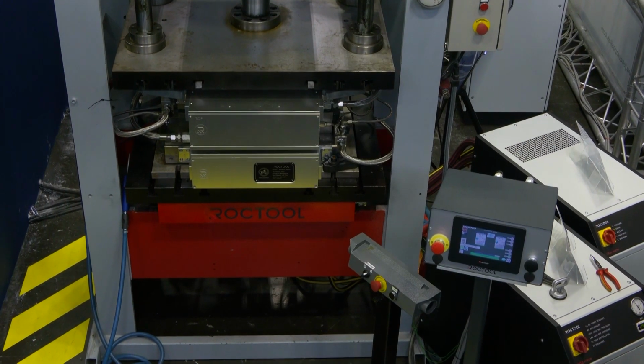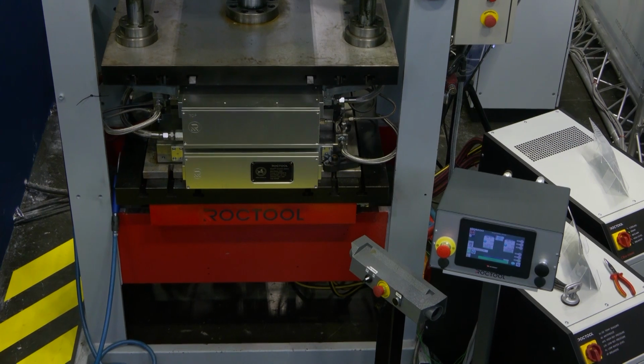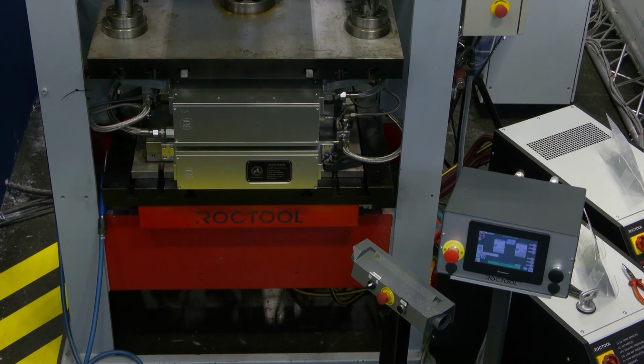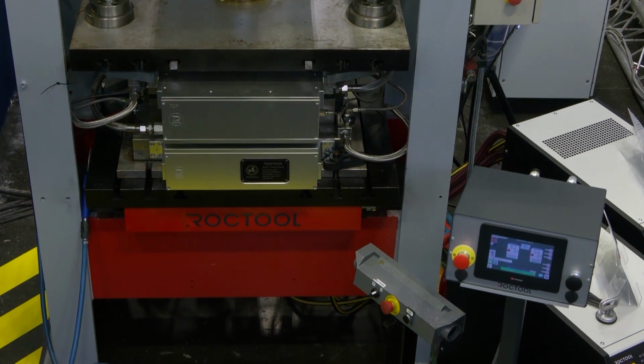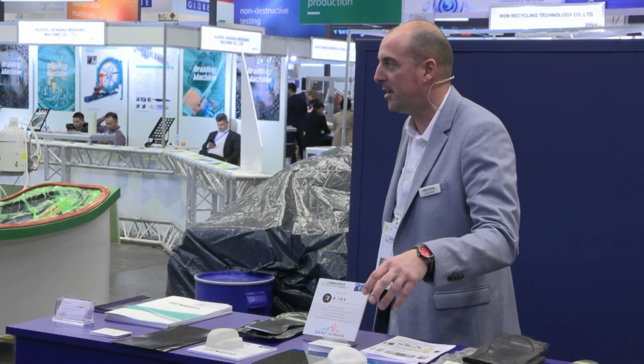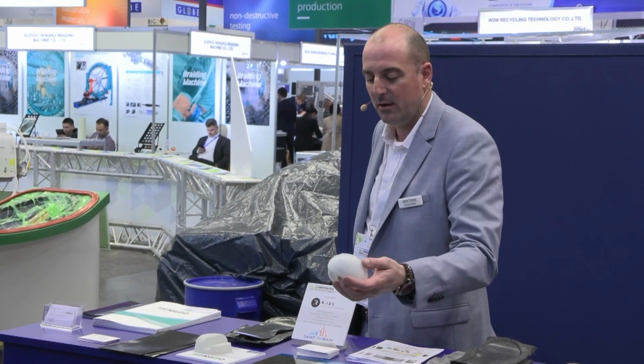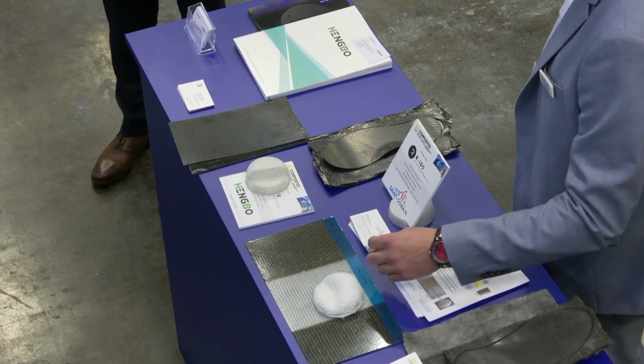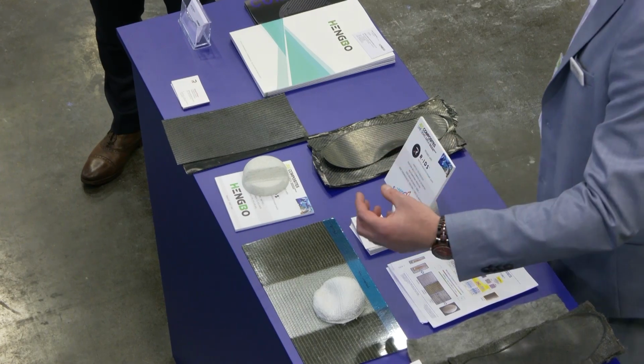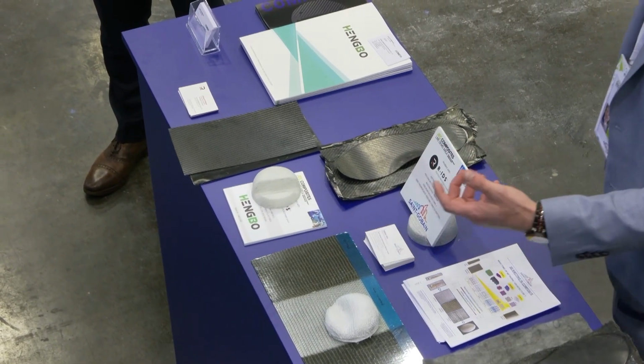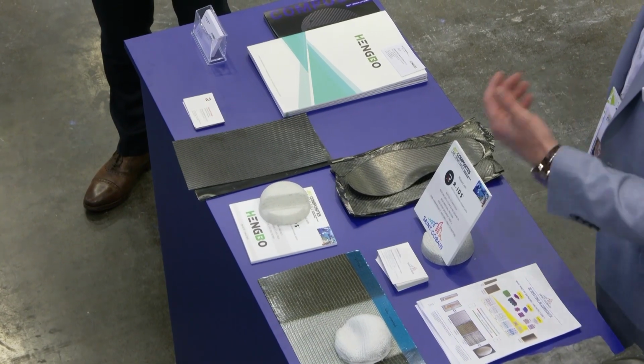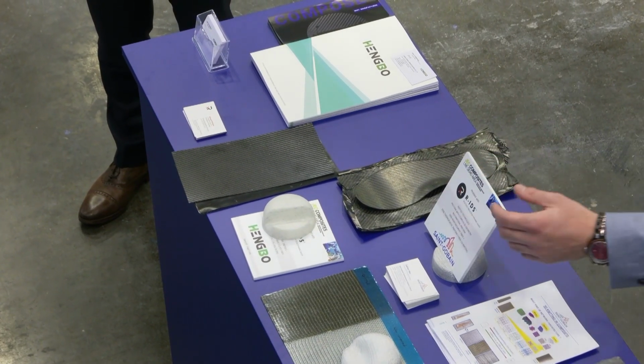We also show you during the live demo several possibilities to use our technology with very different materials. Just a quick explanation about our other materials. The material from Saint-Gobain is a 3D preformed textile, a mix of thermoplastic resin and glass or carbon fibers. The interest is, of course, to have a 3D preform to easily lay up your mold in a short time and, combined with our technology, obtain a very short cycle time, with the possibility to lay up and demold the part in a few minutes.